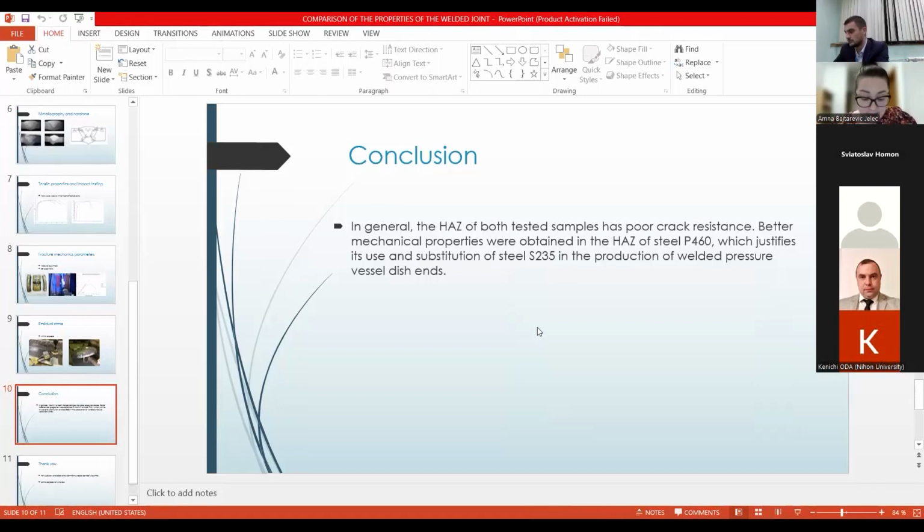We concluded that tensile properties are above the standard prescribed values for the defined materials. Hardness of series 2 is higher compared to series 1. Poor impact properties at room temperature correspond to brittle material behavior. Based on the measurement of residual stresses, it can be concluded that the effect of plastic deformation is positive in terms of reducing the level of residual stresses. And thinner sheets give better fracture toughness results for the same material.